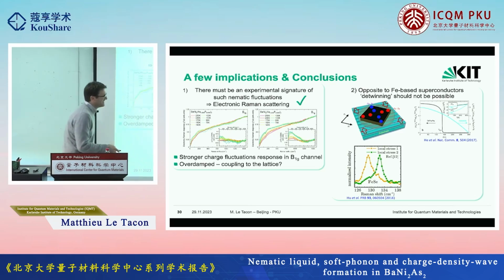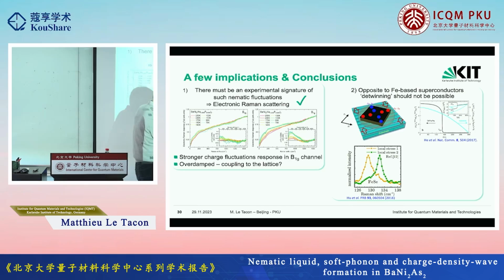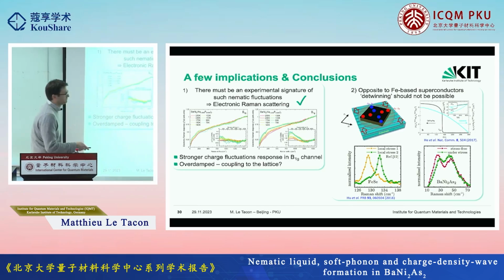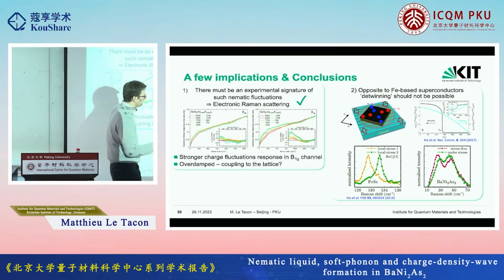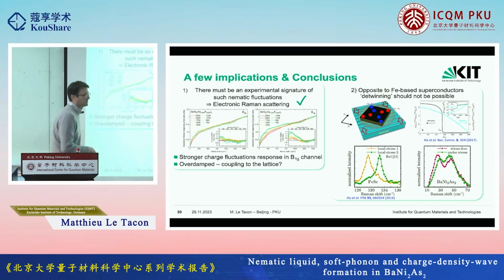That's why it doesn't look so good. But essentially, if you look at the EG mode in the ordered phase of iron selenium, if you apply some stress, you see either one or the other. You don't see the two. As soon as you put some stress, you detwin the system, you see one or the other mode. If we do the same thing on the BaNi2As2, you get a small spectral weight redistribution, but you're never capable of completely suppressing one peak or getting the other, despite the fact that we are using pretty much the same kind of distortion here.